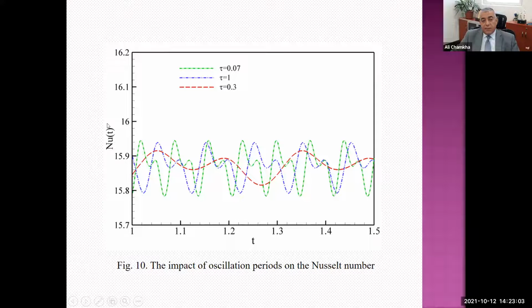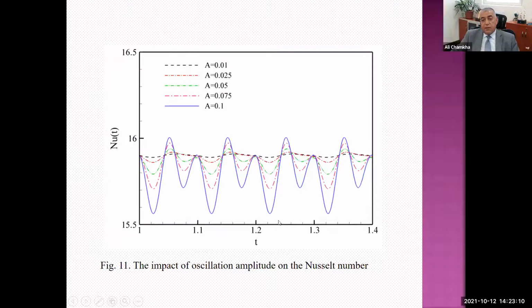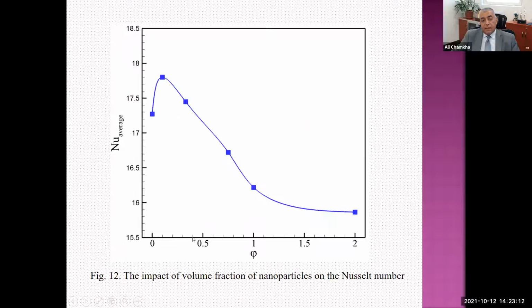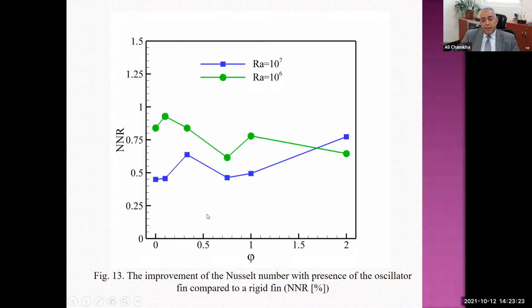This is the Nusselt number as a function of time for different times. Here you can see the colors, and you see the Nusselt number variation. Same thing here. Now, in principle, for this type of problem, as you enhance the volume fraction of nanoparticles, you have, in principle, a reduction in the average Nusselt number due to the oscillation. Same thing here for different Rayleigh numbers. As you increase the Rayleigh number, it decreases, except for high volume fraction.